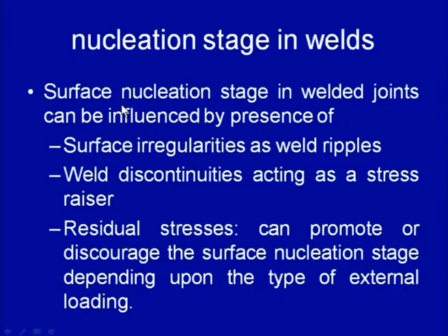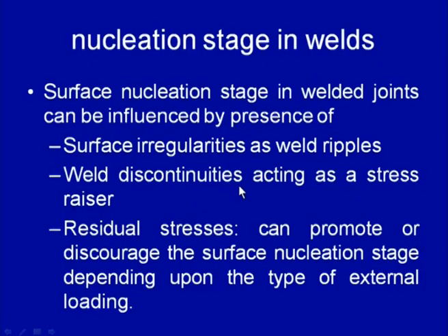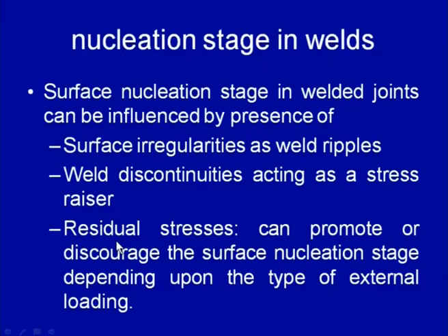approaches. In the nucleation stage, in the case of welded joints, nucleation can be influenced by the presence of surface irregularities, which are usually present in the weld in the form of weld ripples, and weld discontinuities are also usually present in the form of craters, cracks, inclusions, porosities, etcetera, and these act as stress raisers. And apart from these, the weld joints most of the time have residual stresses which can promote or discourage the crack nucleation stage depending upon the kind of external loading.